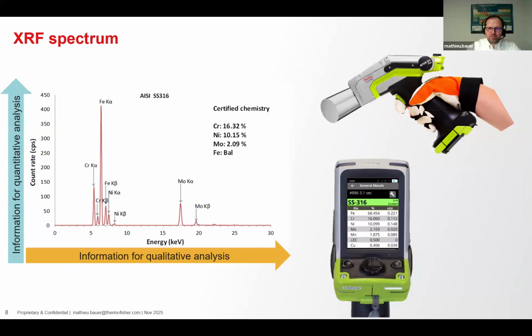On the figure on the left-hand side, we display a spectrum of a stainless steel 316 grade. The spectrum is a bit like the fingerprint of the material. The energy of the photons is plotted on the x-axis, and since the energy is element-specific, that provides us information about which elements are present in the sample. On the y-axis, we have the count rate, and the count rate provides information about how much of each of the elements is present in the sample. As you can see on the spectrum here, we have peaks for chromium, iron, nickel, and molybdenum, which are the main components in the stainless steel 316 grades.